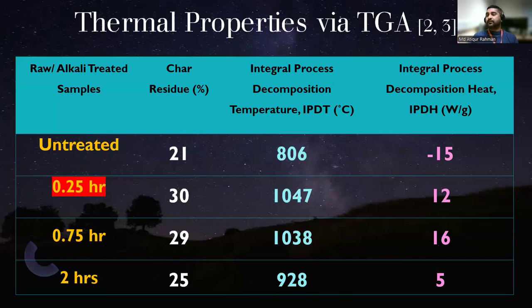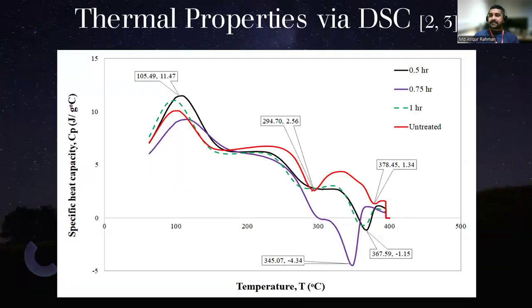There is another value we found from the same curve, which is the IPDH. This is the parameter we introduced for this purpose, and we found that if the IPDH value is higher, it's higher in a positive sense. If it is higher, its heat capacity would be lower. You can see that for the untreated one, it is a minus value, -15. That's because of the presence of hemicellulose. The material got lots of heat absorbance. That's why, rather than being exothermic, it becomes more of an endothermic event, and the value becomes negative. All those treated ones are positive. That has become exothermic, so it is more thermally stable, or you can say it is providing more of the insulation property. Let's see the DSC.